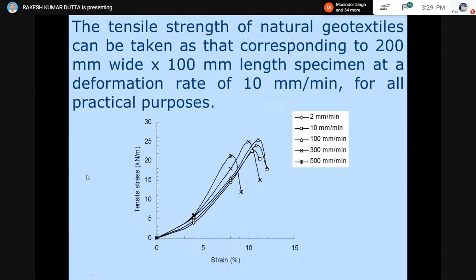Then the same study I have shown in terms of the tensile stress versus strain curves. So again you see here the strain rate used is 2 mm per minute, 10 mm per minute, 100 mm, 300 mm, 500 mm. So all these curves are very close to each other. So that means if you test these materials for the tensile strength using a strain rate of 10 mm per minute, this is going to give you a fairly accurate value of the tensile strength.